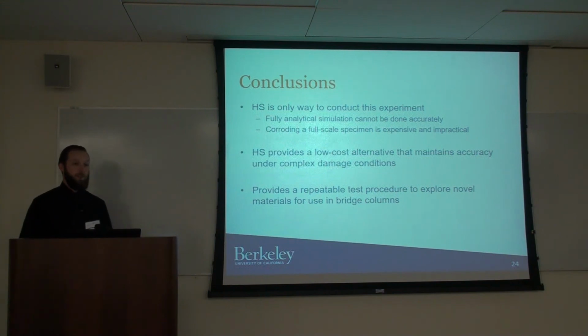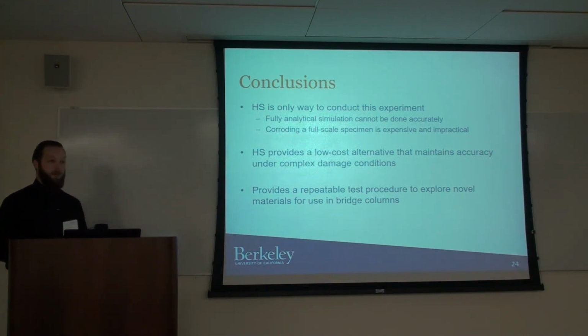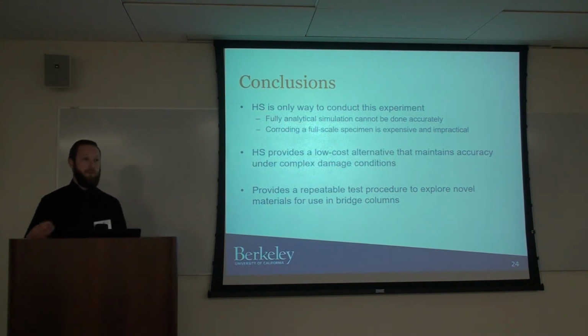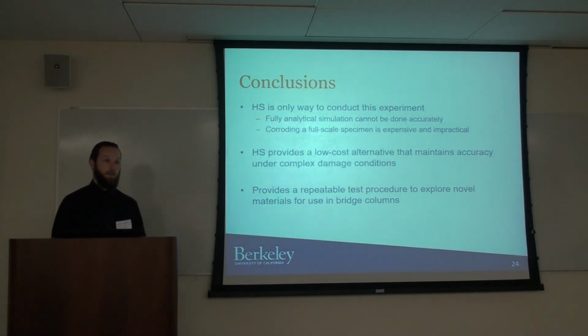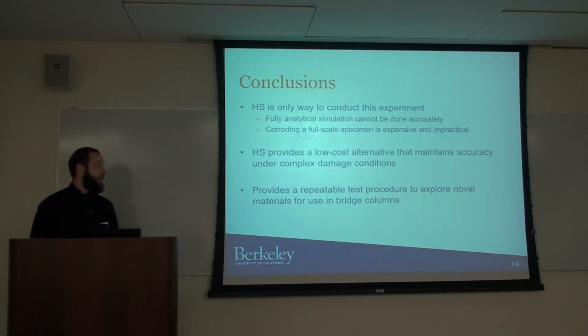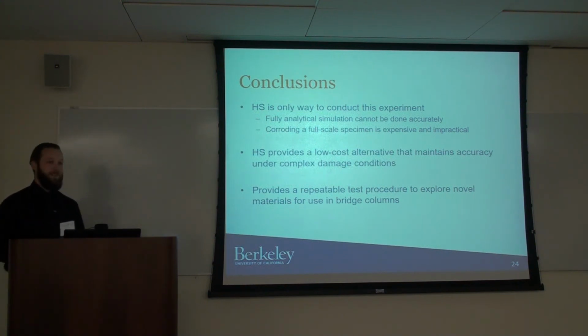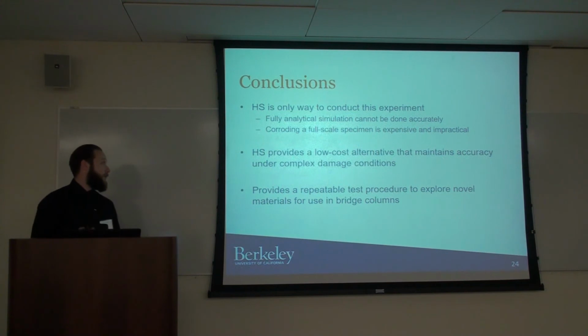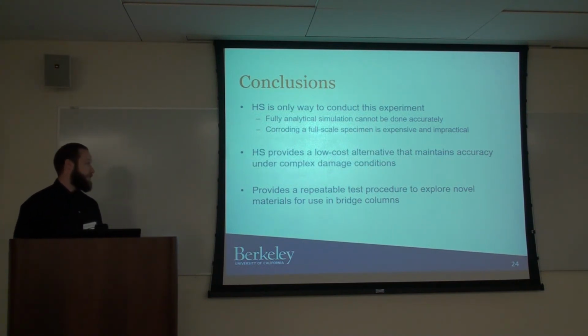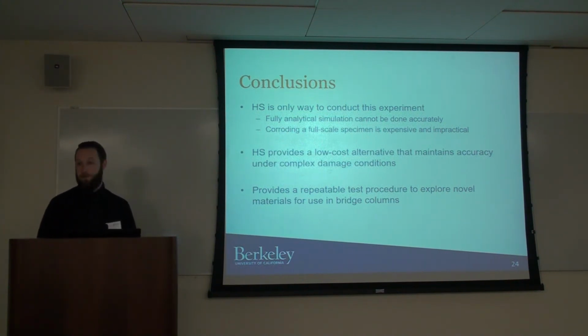And the reason hybrid simulation is significant and important to this test is that it really is the only feasible way to incorporate this durability component with seismic testing. Again, due to the fact that fully analytical simulations cannot be done accurately, and that corroding a full-scale specimen and then performing a seismic test is expensive and impractical. So hybrid simulation provides a low-cost alternative and can maintain accuracy even with complex damage conditions. And it provides us with a repeatable test procedure to explore new materials for use in bridge columns.